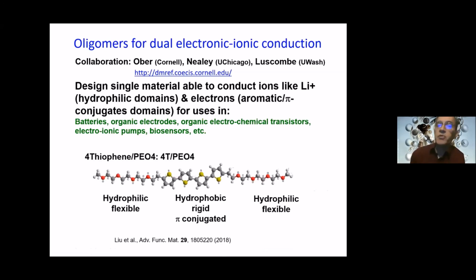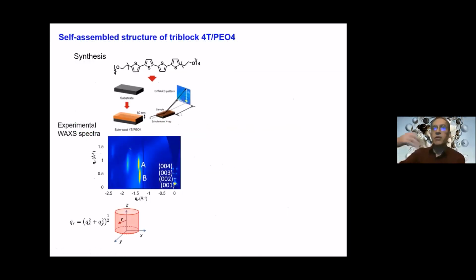So for that purpose, this is one of the molecules we've studied. I'm going to show you results about it. You can see it's a linear tri-block that has a sort of rigid block in the middle, which is hydrophobic. It's pi conjugated, has these thiophene rings. And on the sides, you have these more flexible hydrophilic polyethylene oxide domains. And so our collaborators were able to synthesize, prepare the films, and characterize them in multiple ways, such as, for example, using wide-angle X-ray spectra to see a structure.